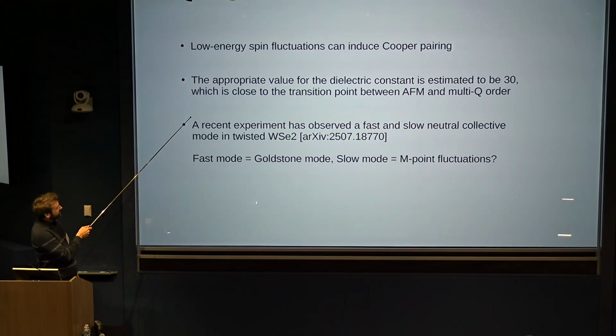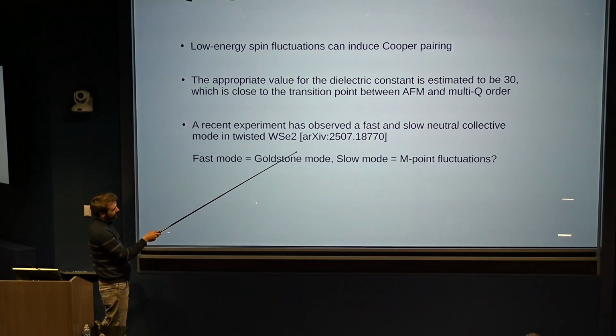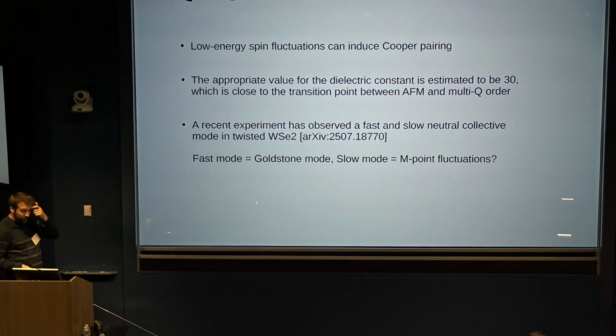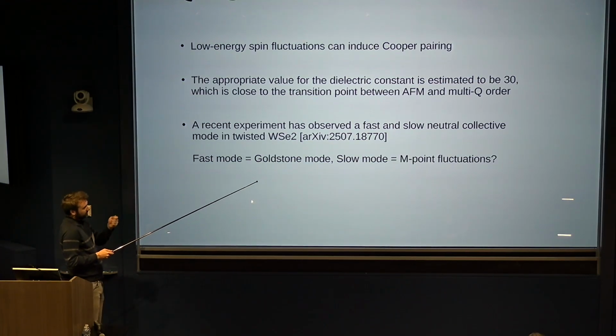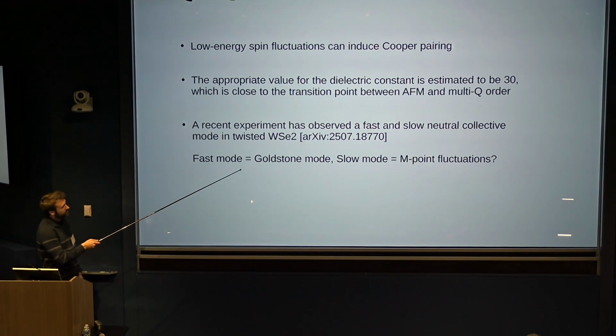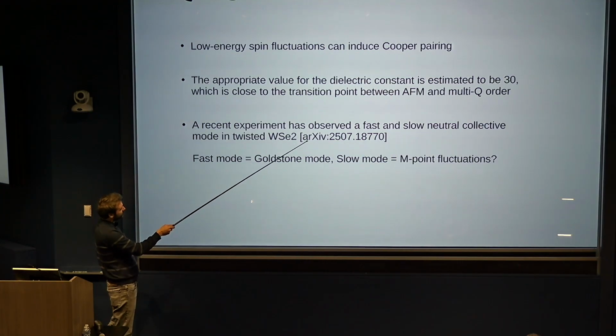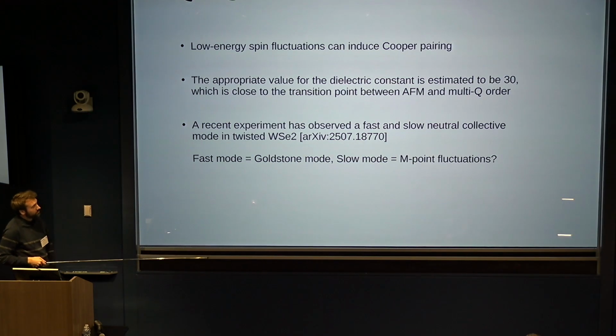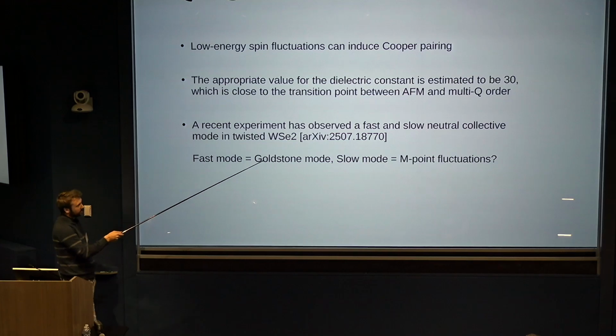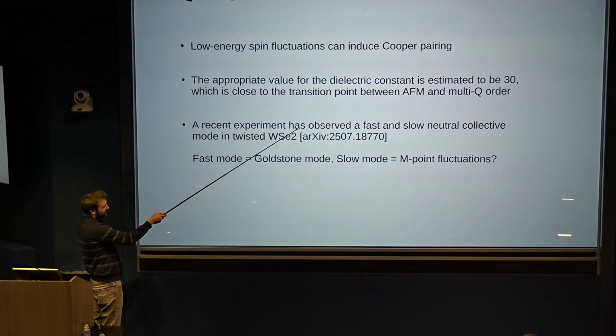And one indication is that you can actually estimate what the correct value is for this dielectric constant that you should use by comparing the layer polarized regime. You can apply a displacement field and then look in your Hartree-Fock, or your self-consistent mean field, at when the electrons basically polarize to one of the two tungsten-selenide layers. And you can do this for different values of the interaction. And you find that if, in the mean field calculations, you use this dielectric constant of 30, then you find the layer polarized regime at roughly the same displacement field as in the experiment. So that seems to be a good indication that you should use this dielectric constant of 30.